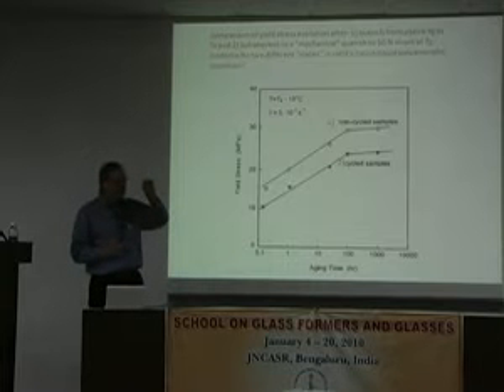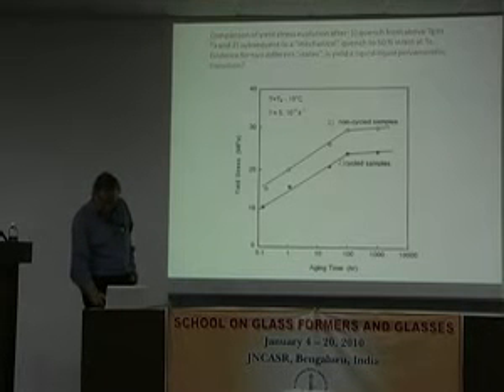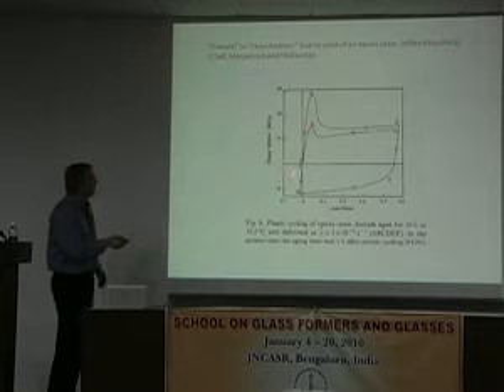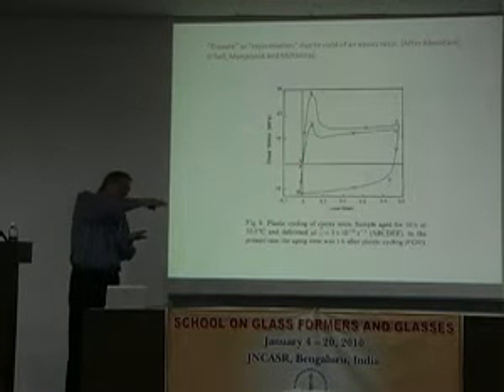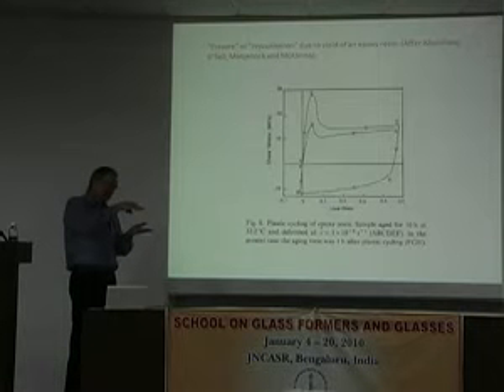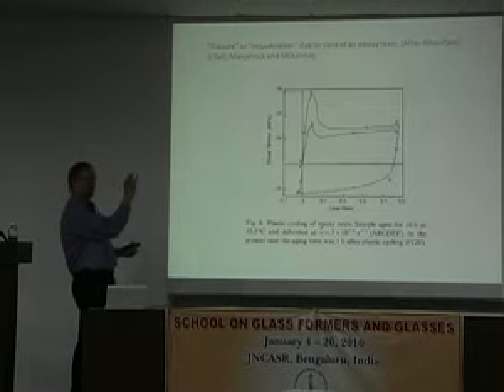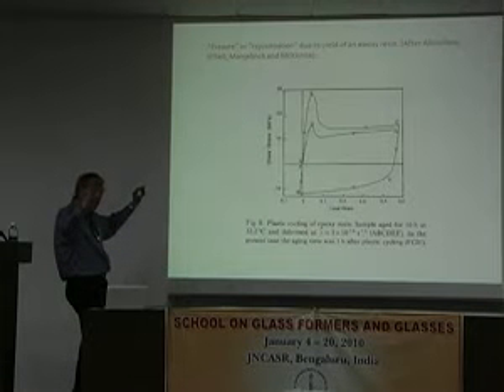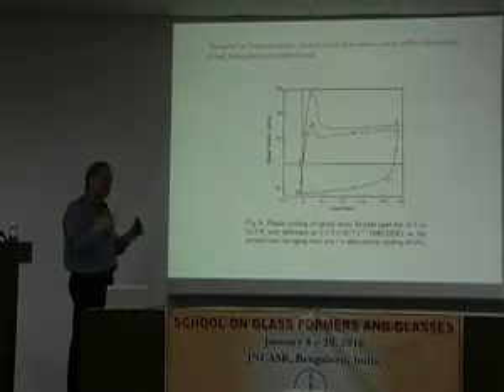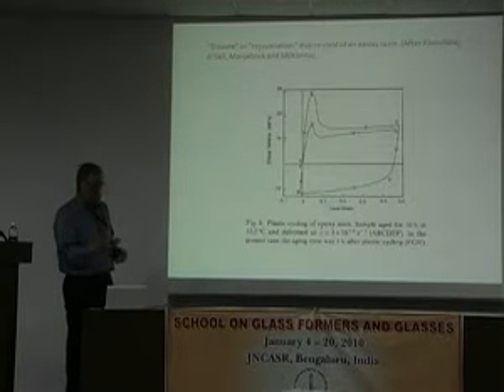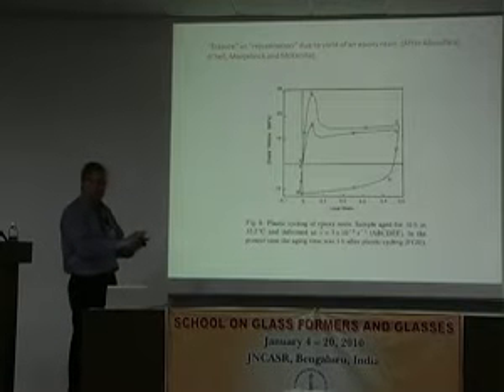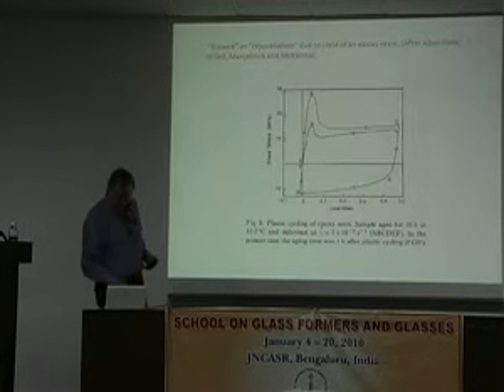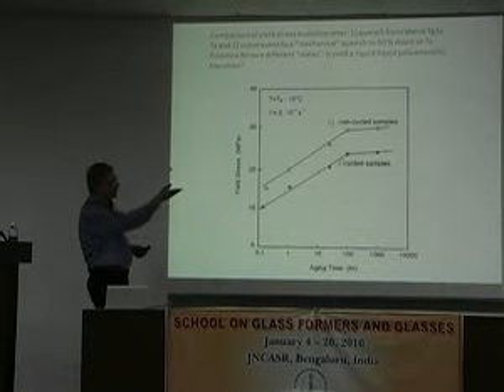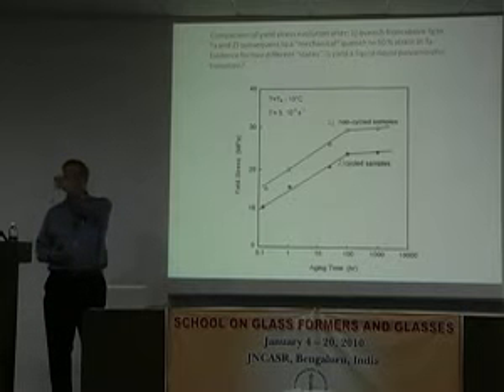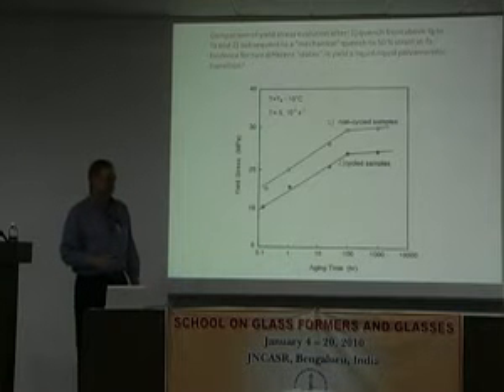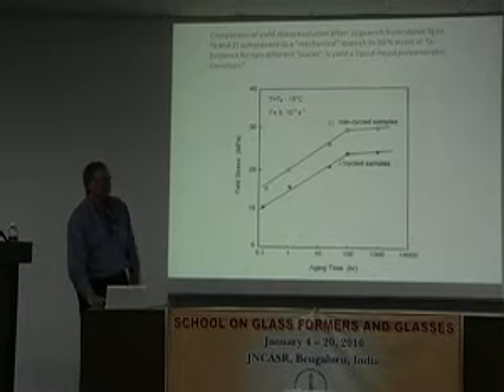Yeah, we actually watch it, in this cycling experiment, you can actually watch. In the case of the way he does the shear, there's a groove in the sample to localize the shear, and you actually watch a shear zone, which has a different index of refraction, propagate the whole width of the sample. And so you can see that. So it appears, at least at the optical level, homogeneous. But I can't say anything about what's happening microscopically. But regardless, whatever it's aging, it's going somewhere else. And it certainly looks homogeneous at the visual level. But yeah, those are all questions to be answered in the future.